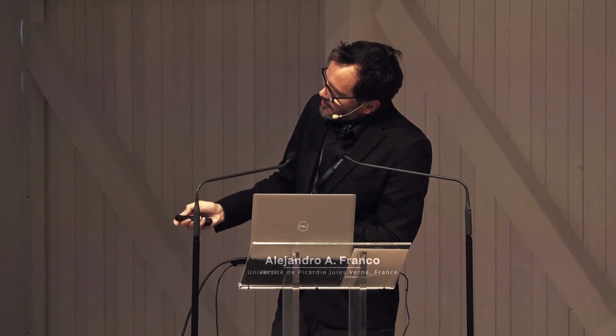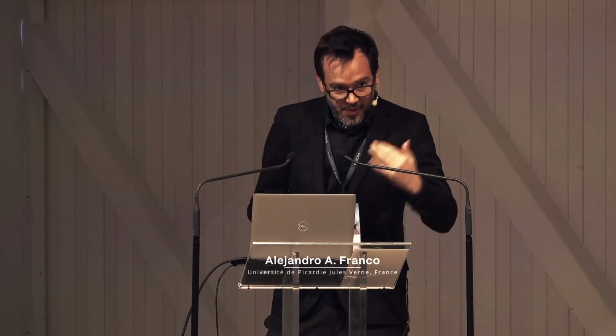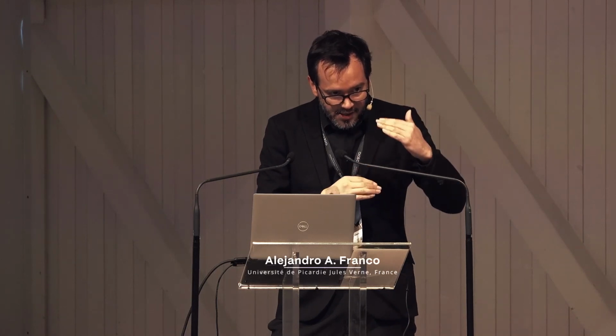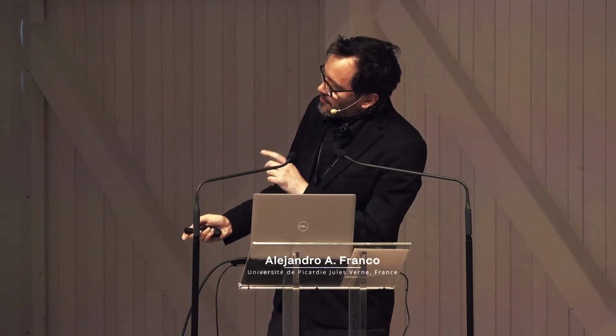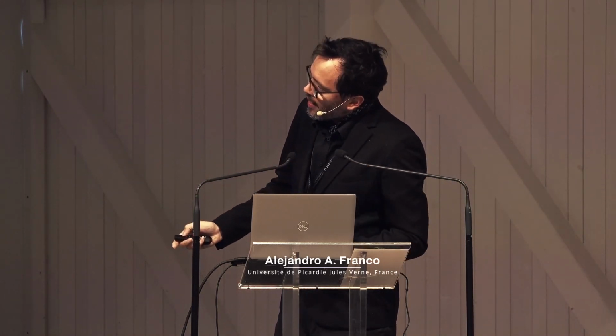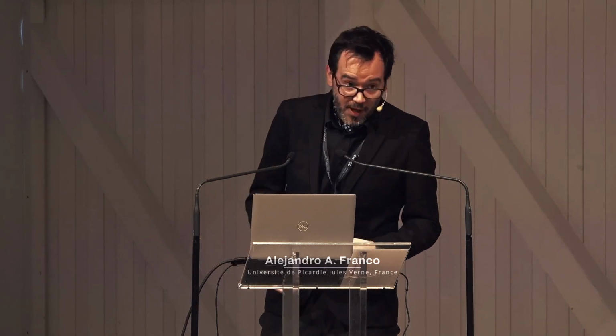Then, once you get this dry electrode microstructure, you simulate the calendering. So here we press the electrodes, okay? Again, you need to do that in reality because you want to improve the electrical contact between the particles. Then you see in the simulation that you have some kind of elastic recovery when you press the electrode, so the electrode relaxes a little bit and recovers a little bit of the initial thickness, but not fully. This is a phenomenon also very well known in industry.